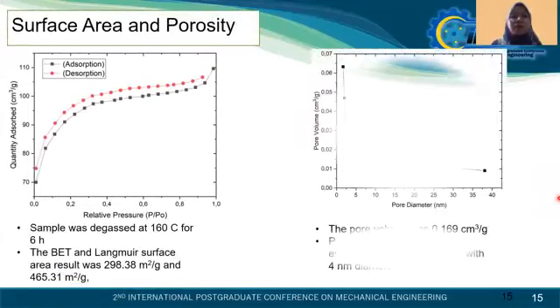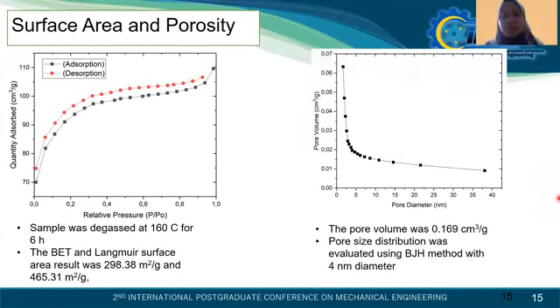And after that, we want to observe the surface area and the porosity, and the surface areas that we got from the BET and Langmuir are 298 meters squared per gram, and also 400 meters squared per gram. And we also do the pore size distribution by using the BJH method, and it gets 4 nanometers in diameter for the MIL-101 NDC.